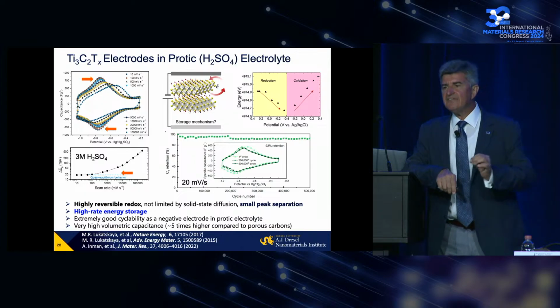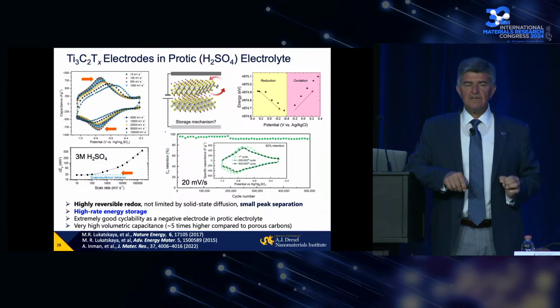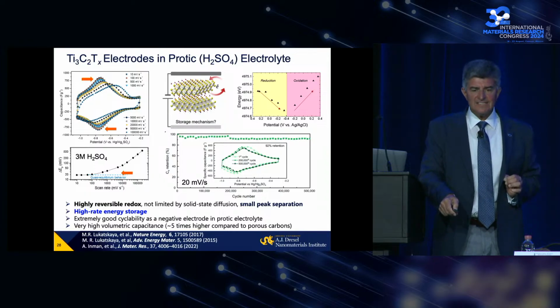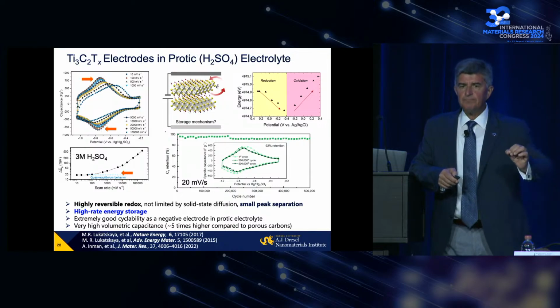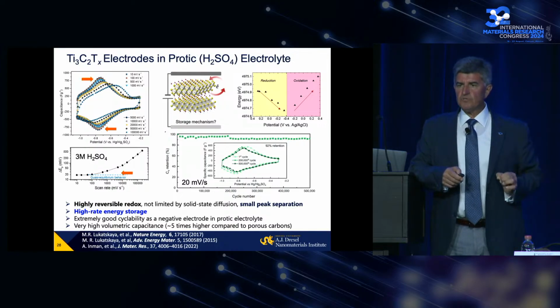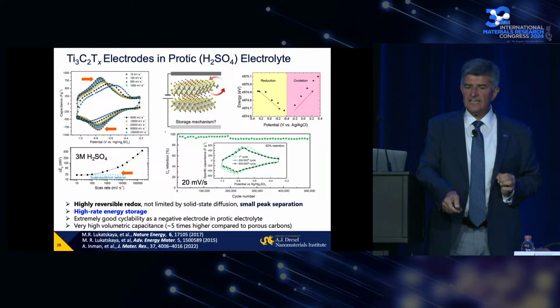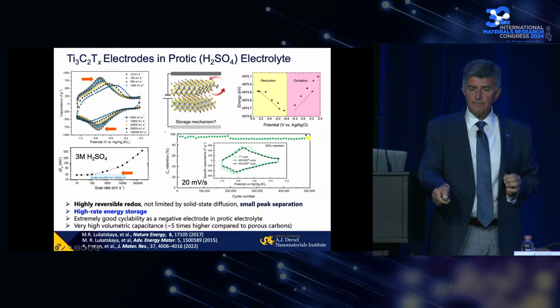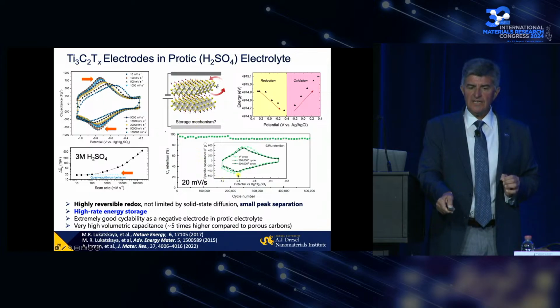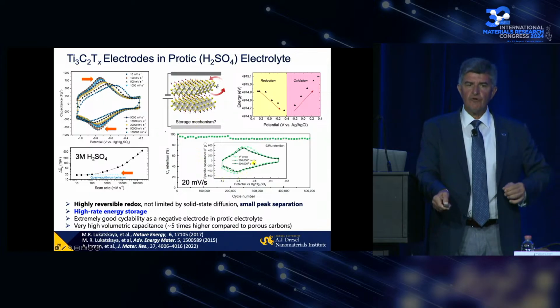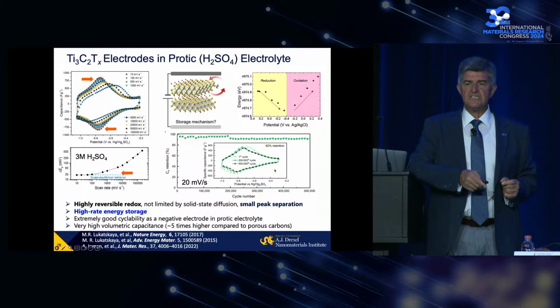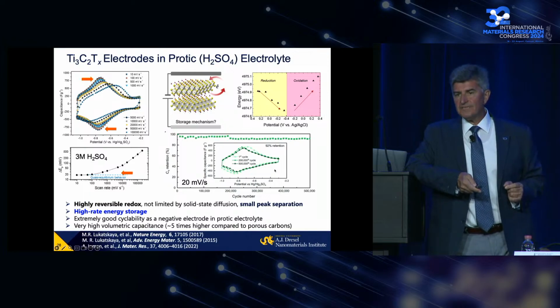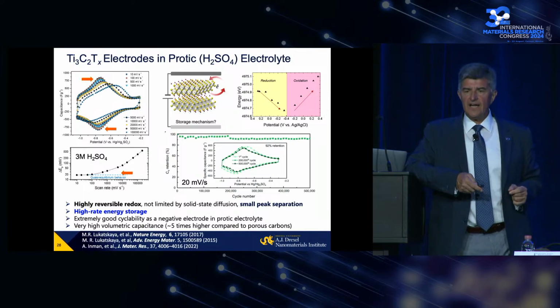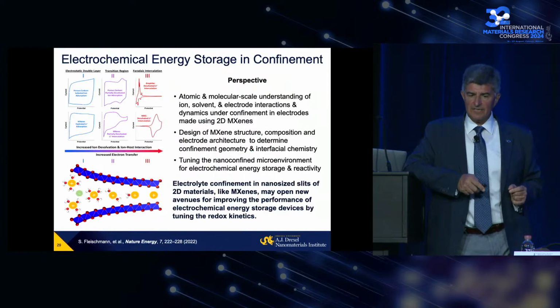So we're not really limited in redox process rate, we're limited in delivering either ions or electrons. And if we do it, we can really have charge storage devices which will just be plugging in, plugging out, or exposing in any other way of charging and get them charged. Moreover, we ran a titanium carbide supercapacitor in acidic electrolyte like sulfuric acid in your lead acid battery for 500,000 cycles with only 8% loss in performance. So it's probably at least 1 million cycle lifetime we can get here.